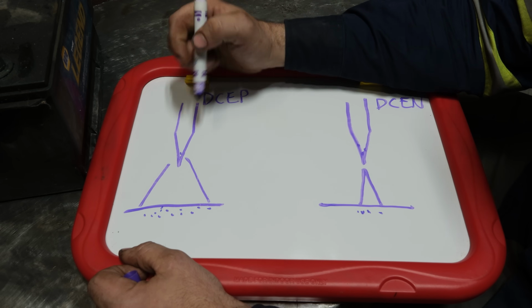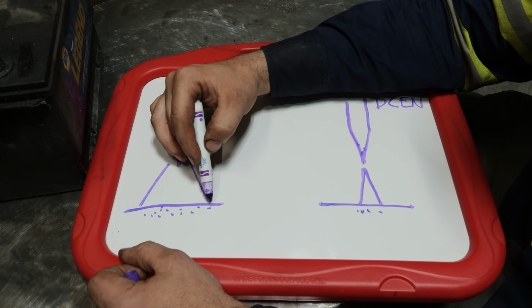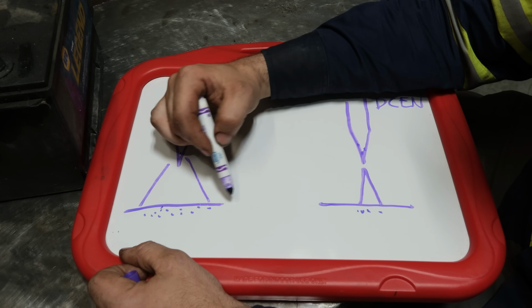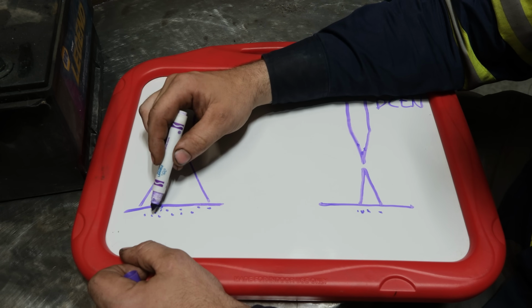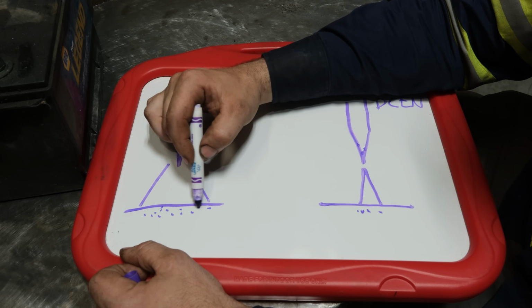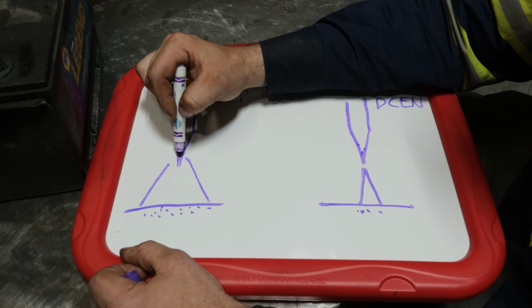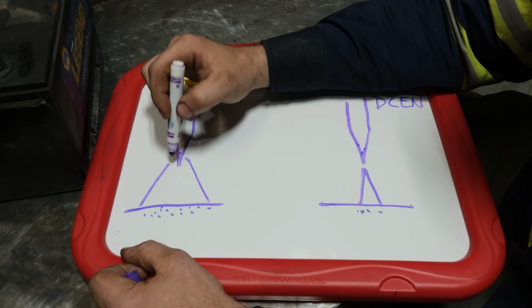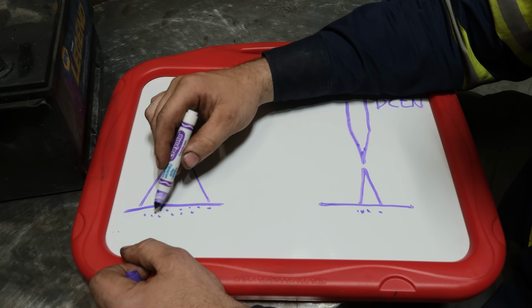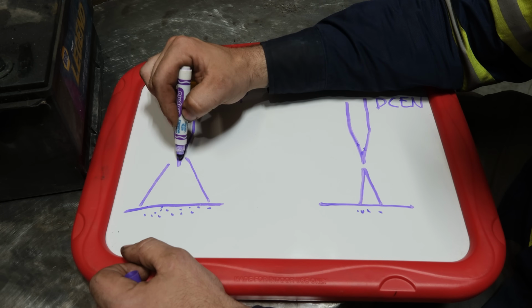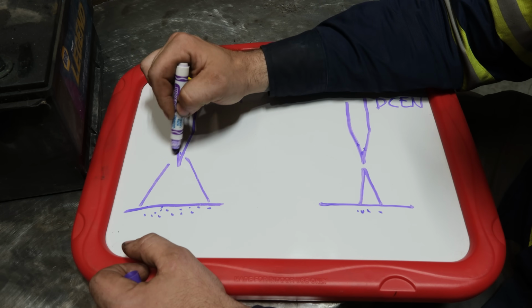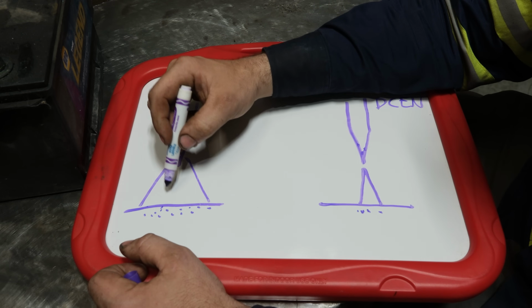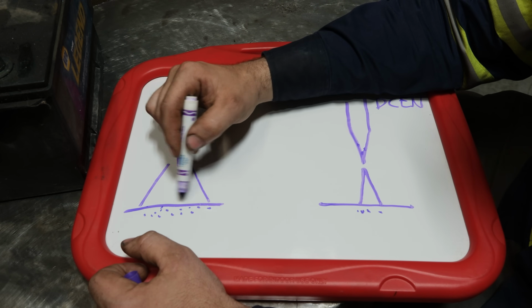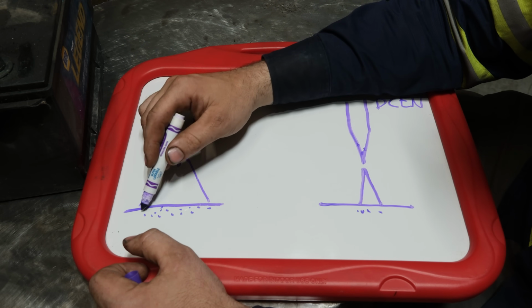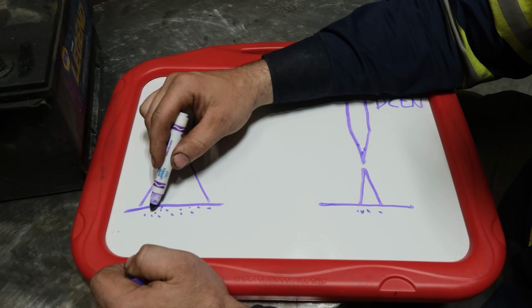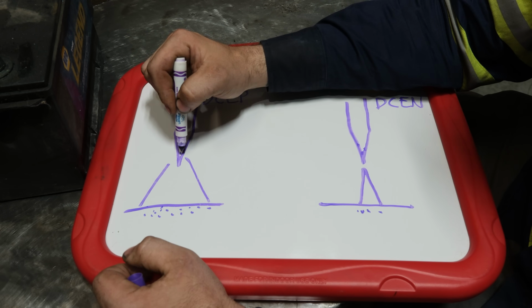On electrode positive, you have a much wider arc cone because you more or less have a flat area or a section of steel where at any point electrons can jump onto the tip of the tungsten. Typically, especially in the case of aluminum, the electrons will only jump in an area that is shielded by gas. So in the case of TIG, argon. So the wider your argon shielding, the wider your area of jumping of the electrons.